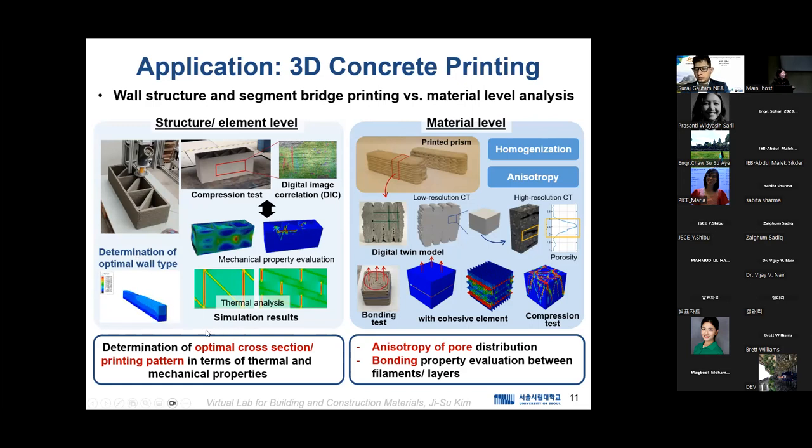the fresh concrete changes its mechanical properties according to time. So we have to select the nozzle speed, the printing speed, and also the width of the structure, or the geometry of the printing structure. So before the actual printing, we can test it several times through the virtual experiment. Then we can avoid wasting material and save some time to develop an accurate and optimized